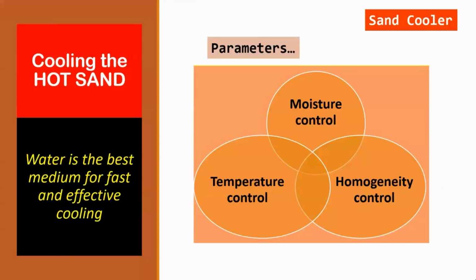What are the parameters for control? One is moisture. Moisture is controlled through two probes, one at the entry and one at the exit. The humidity levels are maintained. And then the temperature is controlled, input temperature and output temperature. Then homogeneity is maintained by the cycle time. How long it remains during mixing is going to decide how much is the homogeneity inside the sand.